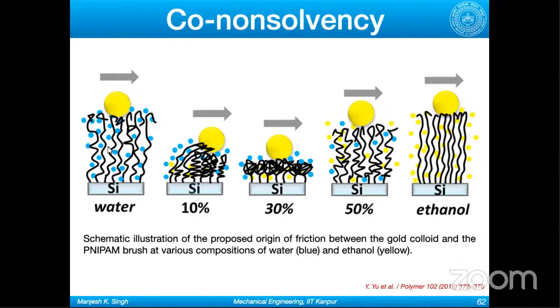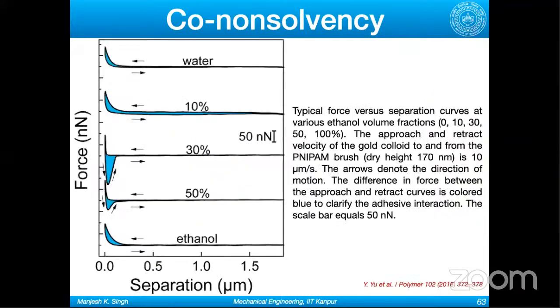So in pure water, you have polymers which are stretched out and forming a brush-like structure. In pure ethanol also, they form a brush-like structure, so you will have low friction. But at a 30% mixture, they're in a collapsed state, so you'll have higher friction, which you can see from this force and separation curve. At 30%, you will see the gap between the trace and retrace curves is very high, which tells you there's high friction force. But in pure water and pure ethanol, the trace and retrace curves are quite close, so you have low friction.